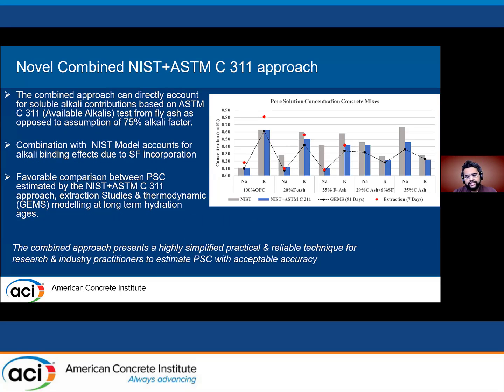So this is a novel technique that was developed in previous research in 2019. This is the combined NIST plus ASTM C311 approach. From our previous discussion, what we have realized is whenever we are considering SCMs or fly ashes, we really have to look at the level of available alkali from these fly ashes, which cannot be assumed as a fixed percentage or a constant value. And this approach actually allows us to incorporate available alkalis based on composition. And when you combine this approach with the NIST model, the alkali binding from the silica fume also comes into play.